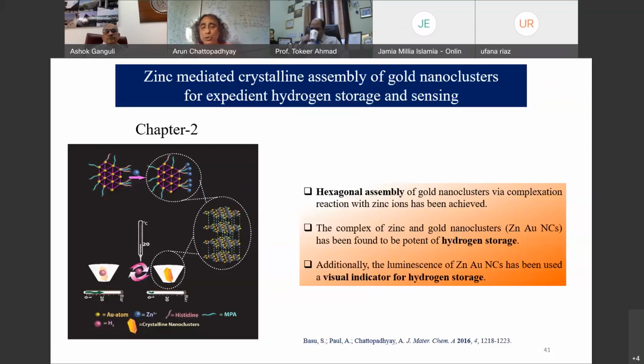So she showed that you can actually take Au14. We have found out the structure, and all that will take a long time to describe. With ligand, then you organize in 3 dimensions using zinc. If you pass hydrogen, this is colored in presence of UV light, fluorescence. In presence of hydrogen, the color vanishes. You remove the hydrogen and it goes.